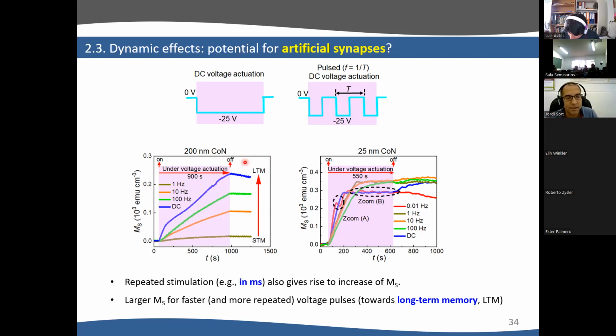And what is interesting, by the way, here is this 100 hertz. This 100 hertz means a stimulus of 10 milliseconds. So this experiment also shows, besides all these neuromorphic things that I will explain in detail later, that with voltage pulses of 10 milliseconds, it is possible to induce magnetization. So chronologically, we went from something where you need 1 hour to induce the effect to something that works already in milliseconds. And this, we think, is a very good improvement.